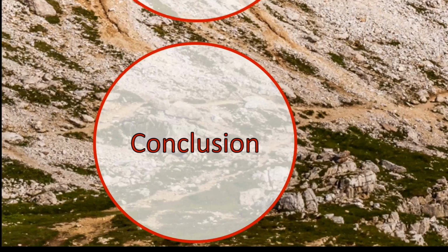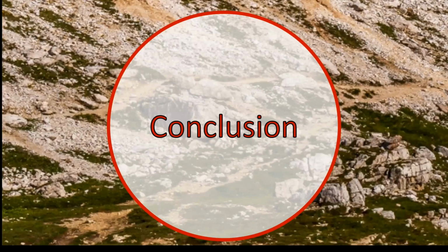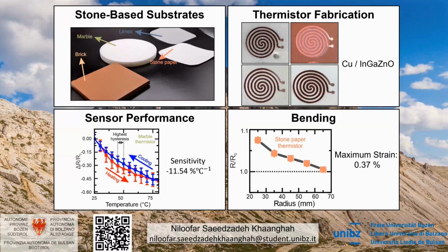In conclusion, here I introduced 4 different stone-based substrates that are environmentally friendly. I used copper and InGaZnO semiconductor, and with a sputtering tool, I fabricated thermistors. And as I checked the sensitivity of the thermistors, the marble thermistor has the highest sensitivity and also very stable signals. And the bending measurement for the 2 flexible thermistors showed that the stone paper thermistor resistance slightly increased going to higher strain. And thank you.